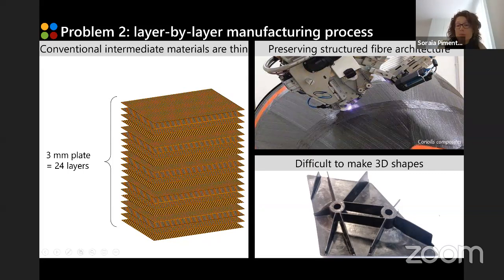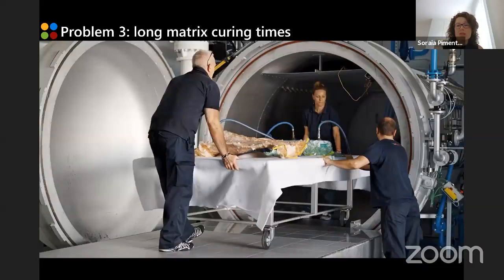A third problem that we have is the fact that after placing our intermediate materials and the fibers exactly in the positions that we want them to be, we still have to cure the matrix. So we need to basically bake the matrix, which can be done under heat and pressure in a massive oven, as you can see here, and that process typically takes a few hours.